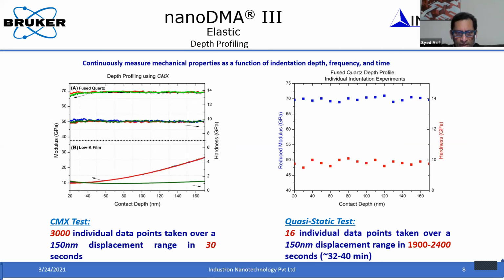That is a big difference in doing this in a dynamic way compared to the quasi-static way, where you have to do load and unload, and you have to do it at different depths at different locations. So it takes much more time, and you don't have a high data density, whereas you can get all that information as a function of depth at a single location within a minute or so, and you can get a high density of data.